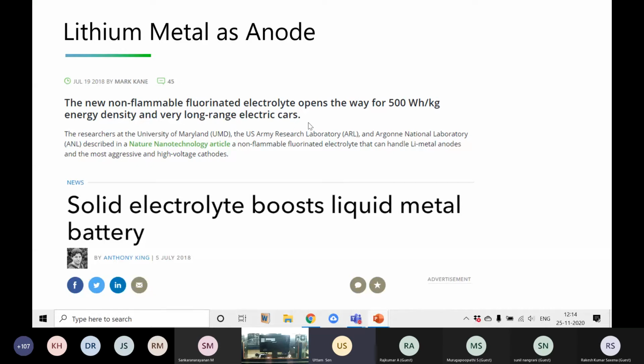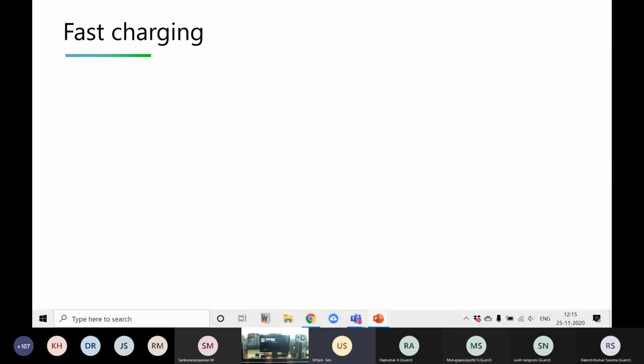Okay, so now see, there are a few reports which were claiming that they started using lithium as an anode, and the energy density is almost double. It is more than whatever the target was. The target was 350 to 400 watt hour per kg, and by replacing graphite with lithium metal, they can increase to 500 watt hour per kg. So you can think that your vehicle range is going to be doubled with the same space.